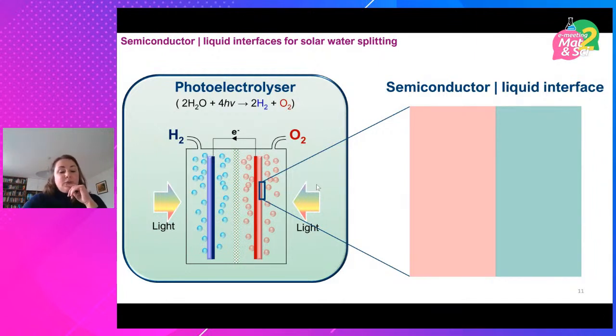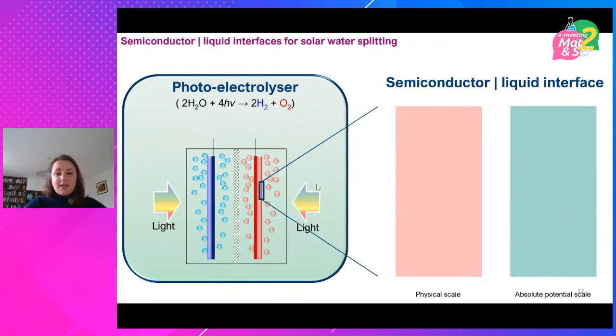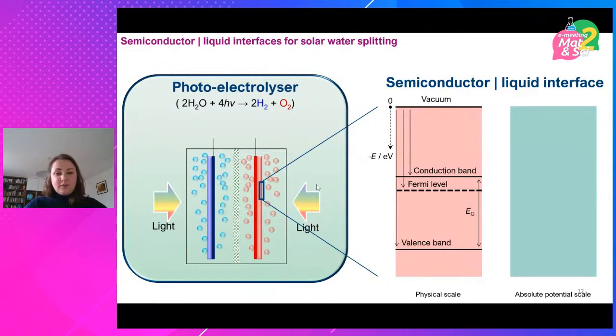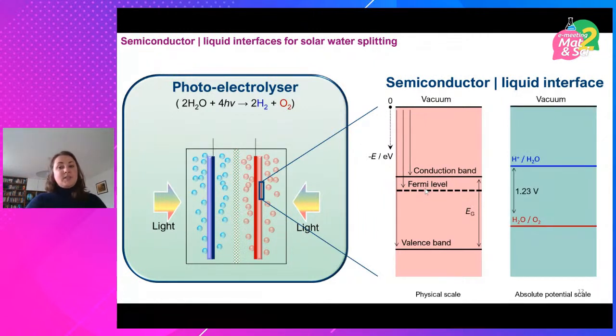The difficulty with the system is that the energy levels of the two systems are characterized by completely different scales. The semiconductor has all of its energy levels reported and calculated on the physical scale, in units of electron volts, and everything's measured relative to vacuum. So conduction band electron affinity is relative to vacuum, and so on. Whereas on the liquid side, we have potentials that are measured relative to a reference electrode, the potential of which is fixed relative to vacuum. So it becomes a puzzle to align these two scales together.